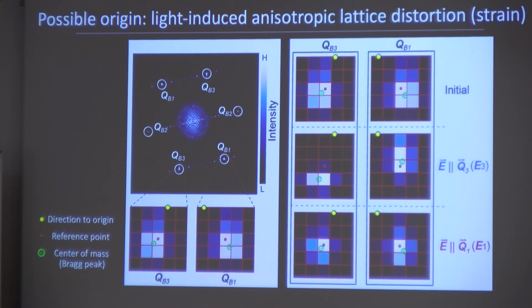The Bragg peak has shifted further away, and therefore the real space distortion is higher. And this one has shifted as well in the opposite direction. And then you apply light along Q1, and the Bragg peak shifts back, see, from here to here. And this one has also shifted. So let me just summarize. What this tells you is that every time the charge density wave intensity gets stronger, the lattice distortion in that direction increases, okay?